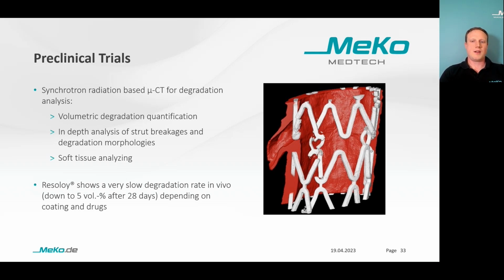Depending on coating techniques, it is possible to generate very little degradation of Resoloy in vivo, down to 5% after 28 days. This is what I mentioned before. In vitro, the degradation rate is much faster, of course. And with that said, I would like to come to my conclusion.